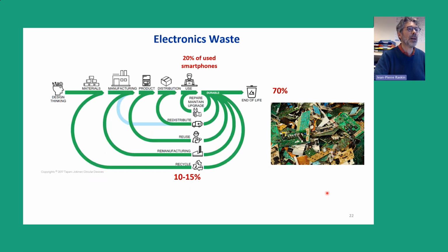Now I would like to finish my presentation by insisting on one stage of electronics which is not really well studied, with nearly no study in the literature, which is the end of life of electronics. If we just look at numbers, most of the electronics, unfortunately, go to landfill, approximately 70%. Only 10 to 15% are recycled. And when we say recycled, it means trying to retrieve some of the materials out of these electronics. Of course, the best would be to repair and reuse those electronic devices, and there is an increase in the market of repair and reuse of, for example, smartphones here. But still, keep in mind that unfortunately, there is no real solid solution for the end of life of electronics.